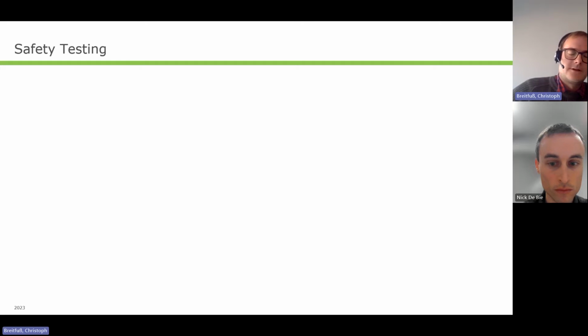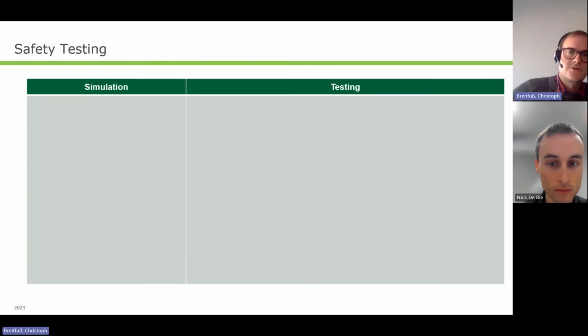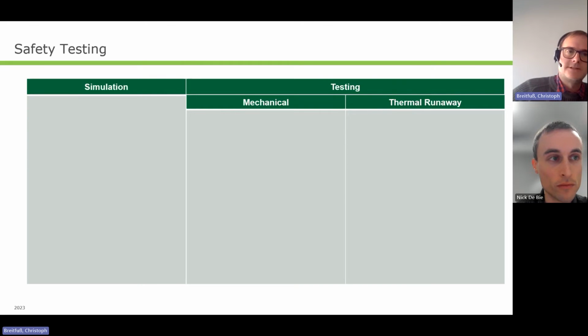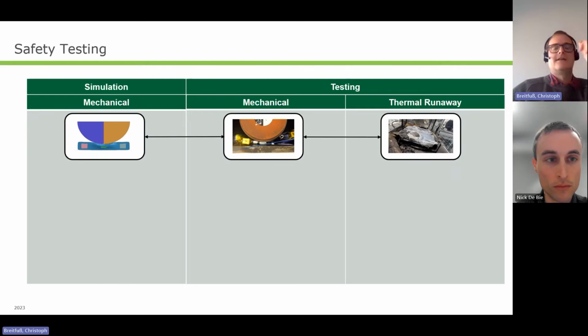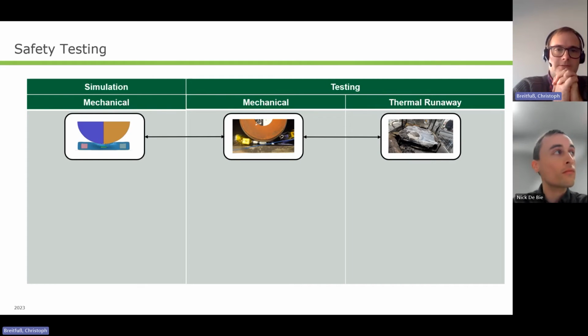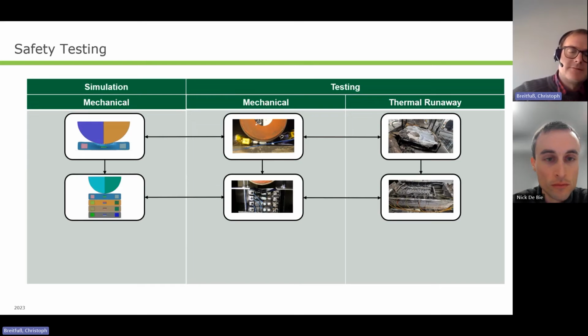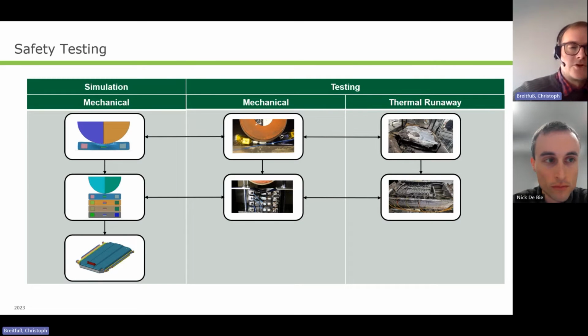For achieving this, we have a hybrid approach, which is a combination between testing and simulation. Testing is subdivided into 2 different parts, mechanical testing and thermal runaway testing, and simulation we do only in mechanical matters. On cell level, we have everything. So we have our mechanical tests, thermal runaway tests, and we can make our mechanical model out of the mechanical tests. Same for stack level, we have everything. On pack level, we have to do an upscaling approach. That means we cannot test a pack, we only have one due to resources and costs. So we are doing this upscaling virtually and have to estimate the reaction of the whole battery pack.